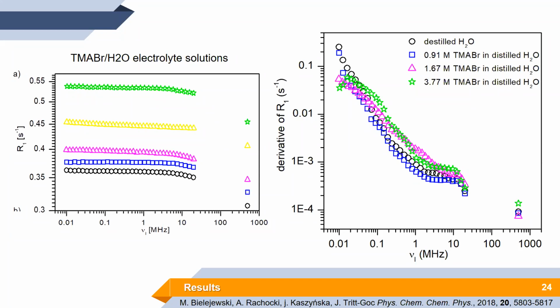But if this would be the explanation for this effect, when we analyze the derivative of the R1, the relaxation rate, then we would observe the shift of the inflection point, which is the point where the curve changes its slope. So what we see on the right figure actually shows that the inflection point stays for all systems at the same place, starting from non-ionic distilled water and ending at the very high concentration of the ions in the electrolyte solution. Moreover, the value of the magnetic field frequency, which is 10 megahertz, is also very characteristic. So this data does not support that the increased relaxation is due to a change of the viscosity.